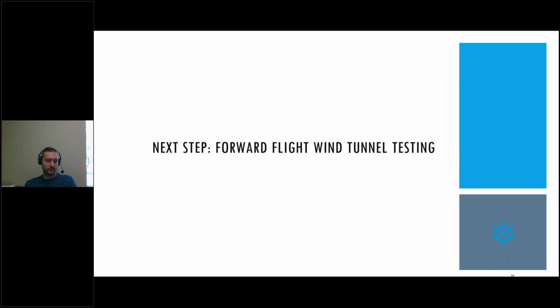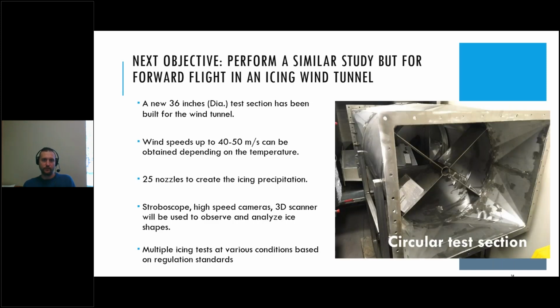So the next step in our experimental testing will be the forward flight in the wind tunnel. Next slide. So this is going to simulate the forward flight of the drone in aircraft mode. So we have built a new 36-inch circular test section for the wind tunnel, where wind speeds can go up to 50 meters per second, down to minus 20 degrees Celsius. We have 25 nozzles to create the icing precipitation.